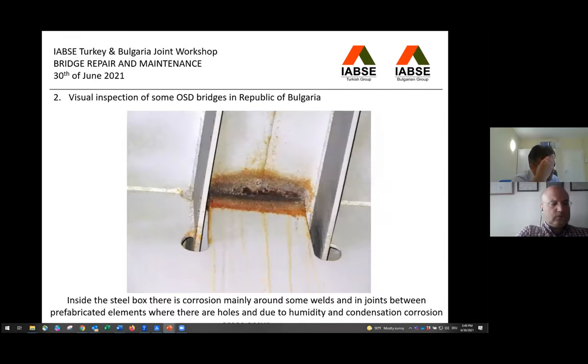In Viaduct 2, most of the problems that we recognized were not cracks, but some corrosion zones. Another thing that is also good to mention is that the open flat stiffeners are passing continuously through the web of the crossbeam, but they are only one-side welded. This was normal practice at the time when this bridge was designed and built, but from today's point of view, this detail is no longer allowed in the Eurocode, because of the eccentric load transfer and future fatigue problems.